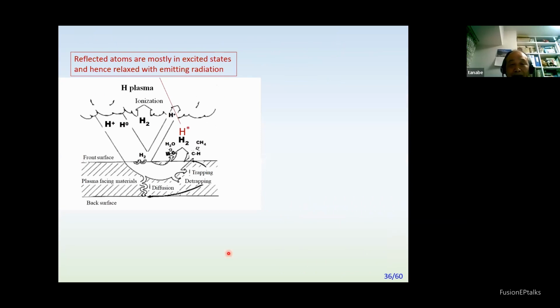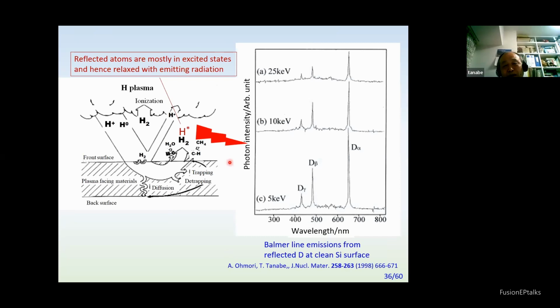This is clearly seen from the Balmer line emissions. In case of reflection, particles come up as ions or excited atoms, and excited atoms give off emission this way. So the higher the reflection coefficient, or the lower the energy, the higher the intensity becomes. At higher energy, reflection is quite small, and the average depth is large, so the intensity becomes low.